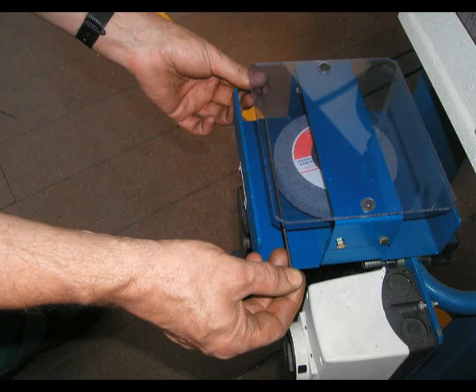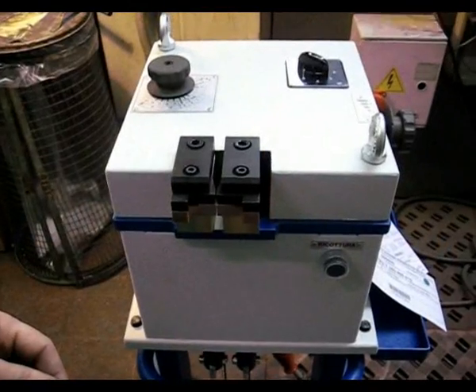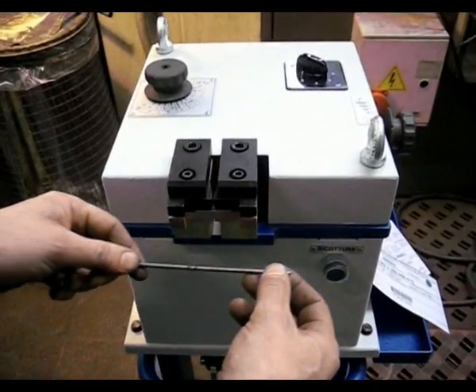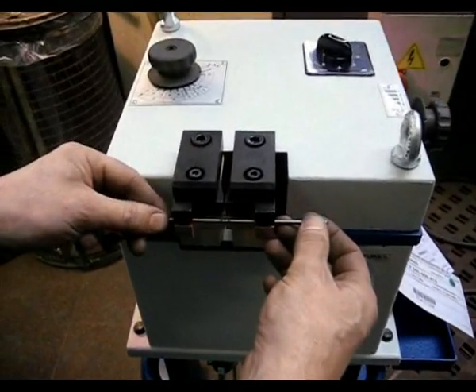For high carbon rods, annealing is necessary. After welding, burr must be removed before annealing operation. The welded wire must be positioned in the outer part of the jaws.